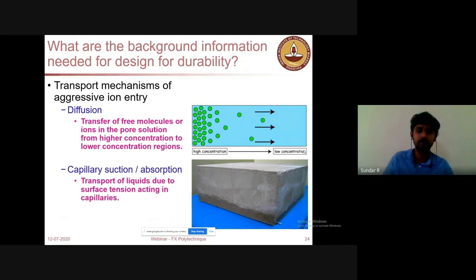So let us have an idea about the processes which bring these harmful elements into the concrete. Diffusion is the process where a higher amount of certain salts in one region moves to the region where the concentration is lower. This is a very common mechanism in deterioration processes. Similarly, capillary suction or absorption: when the concrete is sufficiently dried for a period of time but suddenly comes in contact with water, you could see a sudden ingress, a sudden pull of water entering through the pores, and that will again bring some salts into the system. When we have salts like sulfates and chlorides in the water, they will also go into the concrete with this sudden capillary pull.